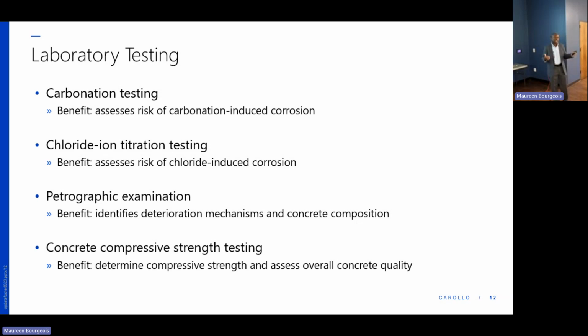How do we test for the carbonation? Well, when WJE takes it to the lab, basically, they take the core sample and they add a solution called phenolphthalein. So think about a chemical. They add it, and depending on the color change, they are able to tell the amount of carbonation that has taken place on the concrete core. Another lab test that is done is the chloride ion titration test.